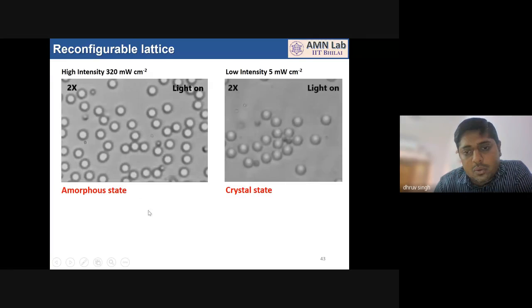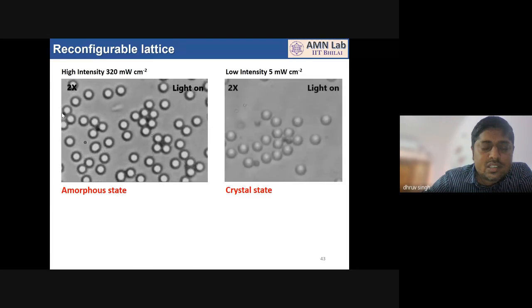And if I grow the assembly at a higher light intensity and at lower light intensity, light is basically doing nothing but controlling the interaction strength. So if I grow it at the higher light intensity, then I end up with the amorphous state. Interaction strength is high. Particles are attaching at random locations, so they are breaking the square symmetry. And when they join and fuse, they form the disordered state, because in the very starting stage, the square symmetry of a particular unit cell is broken.